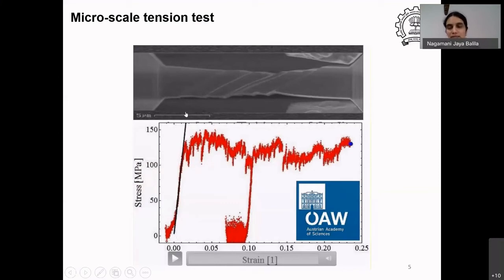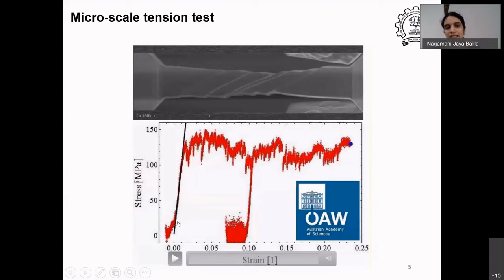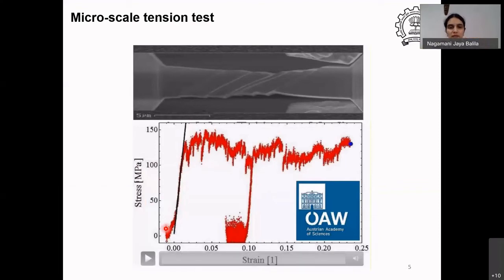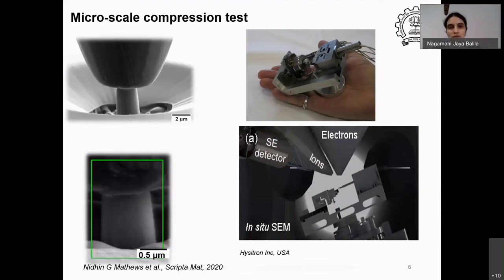You can see that there is a portion which is linear elastic with a straight-line slope from which you can calculate the elastic modulus — the Young's modulus. But you also see that initially the loading is not straight; it has some problem here. This is the part of the data you have to avoid, and it comes from experimental error. When you clamp a specimen which is so small, you cannot hold it very tight initially, so you end up holding it a little loose. That is the pre-stress region. After that, when you continue to pull, it becomes straight and shows the material behavior.